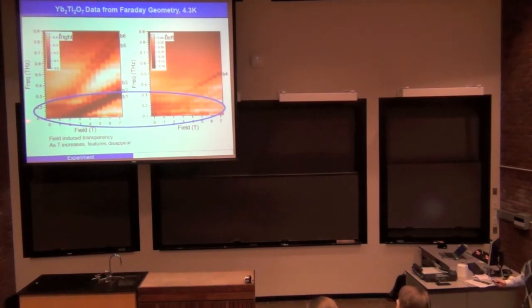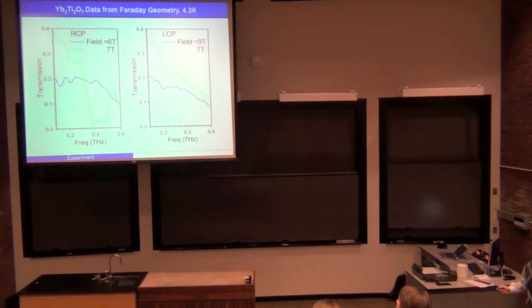So this we call a field-induced transparency, which means as we apply a magnetic field, the transmission in the low frequency range is actually enhanced. And this also appears in the left circular polarized channel. And as temperature increases, all those features disappear. So this shows you the field-induced transparency in different plots, comparing the transmission at zero field and at 7 Tesla. We can see at low frequency range, as we increase the magnetic field, the transmission increases dramatically.